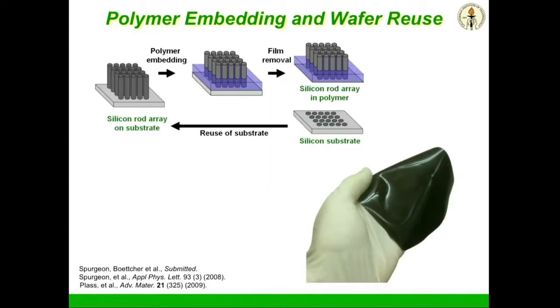They look kind of like this. They look like jellyfish when you make them on a 6-inch wafer out of PDMS. But the next critical step is, what do we do in the process? We grow from cheap chlorosilane, it's a waste product in China, and we take our silicon fibers and impregnate them with our polymer and then give it a rip, like a Band-Aid cutting off your skin with the hair, and we're left with these little stubs.